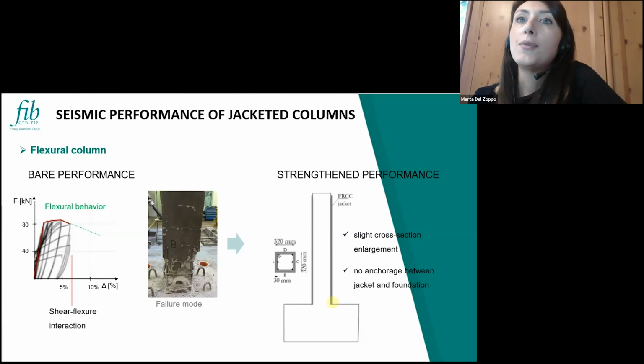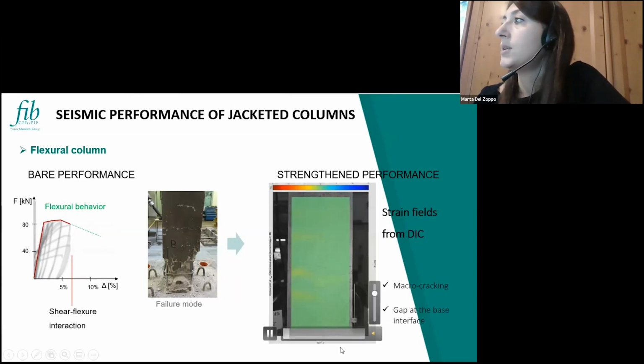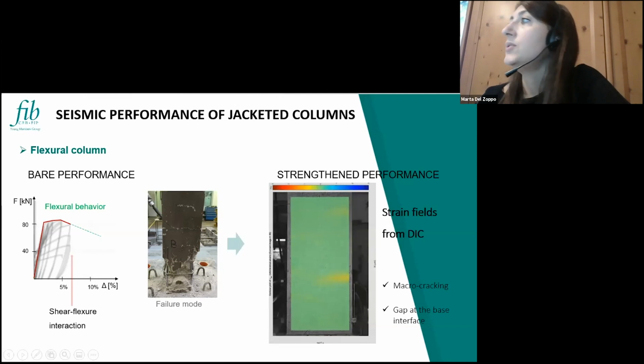Of course, in this case, we are slightly increasing the cross-section from 300 to 320 millimeters. And we are not adopting any kind of anchorage system between the jacket and the foundation because we don't want to increase the flexural capacity of the specimen, but just to look at the possible increase in ductility. So this is the behavior of this specimen during the test.